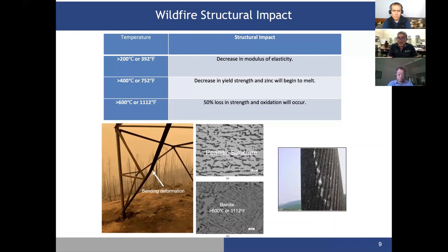And also please note that upon exposure to higher temperatures above 780, 800 degrees Fahrenheit, you will actually melt zinc. And this is exhibited in the photograph on the right-hand side. You can clearly see zinc is melted. And this says to all of us that the corrosion protection is no longer there because there is no zinc on the structure.